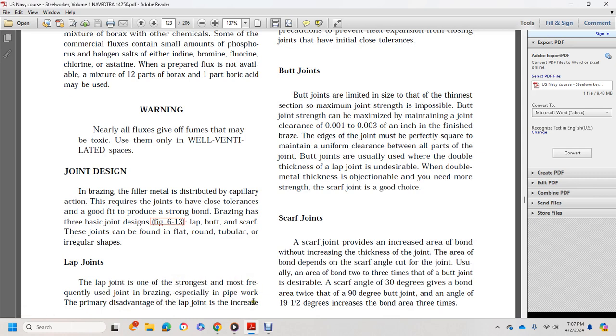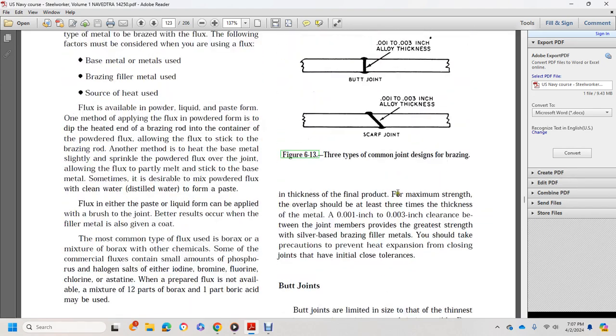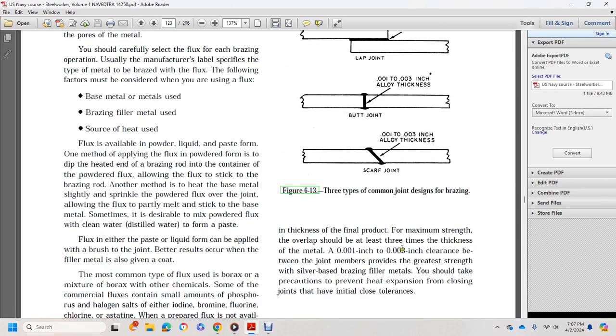The primary disadvantage of the lap joint is that it increases the thickness of the final product. For maximum strength, the overlap should be at least three times the thickness of the metal. A clearance of 1/1000 to 3/1000 of an inch between the joint members provides the greatest strength with silver-based brazing filler metals. You should take precautions to prevent heating expansion from closing the joint at the initial closing tolerance.